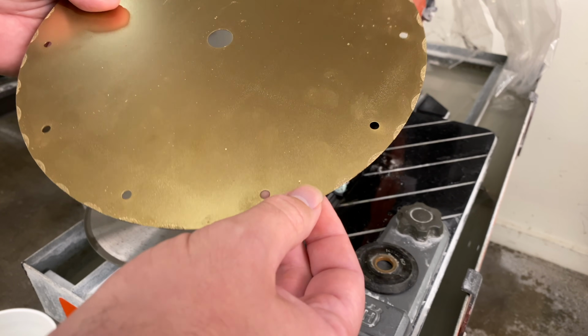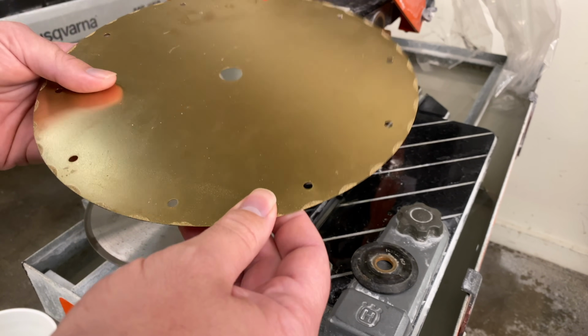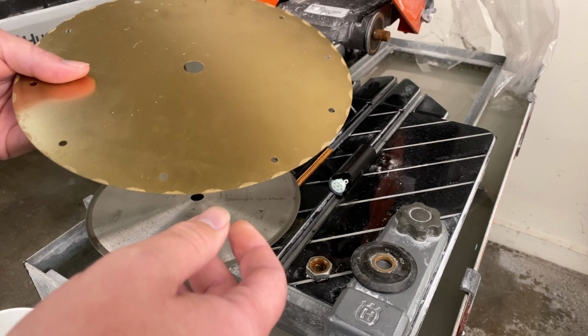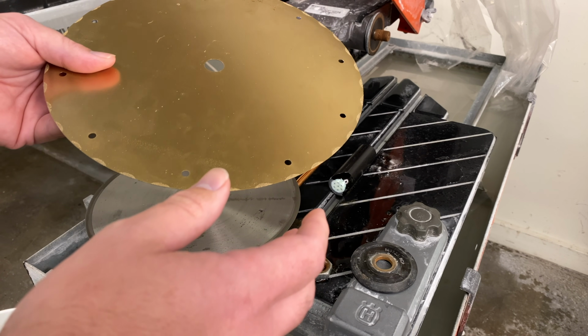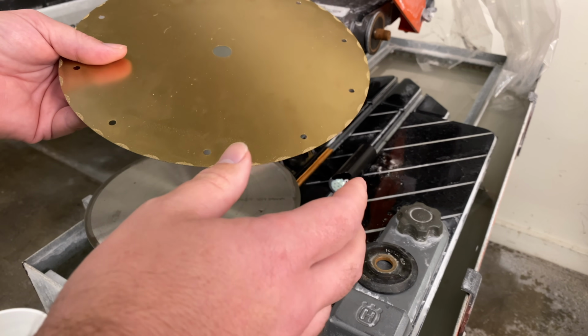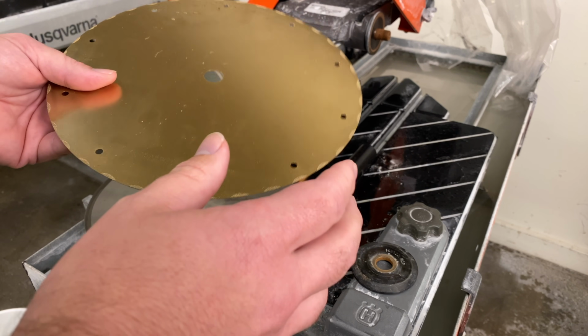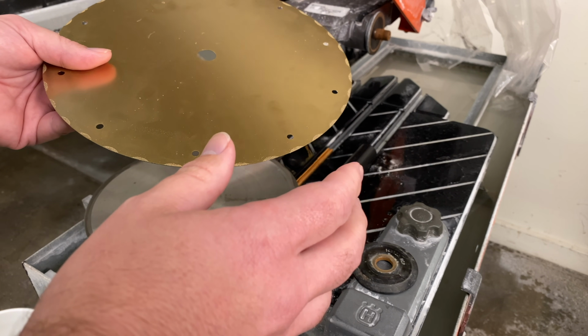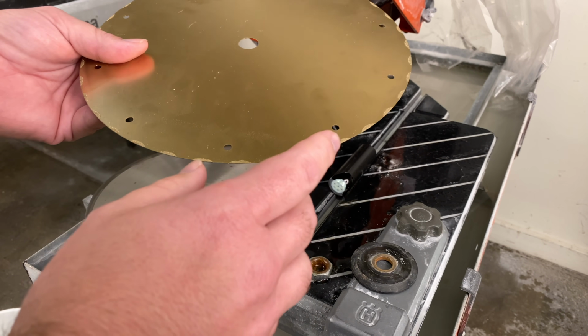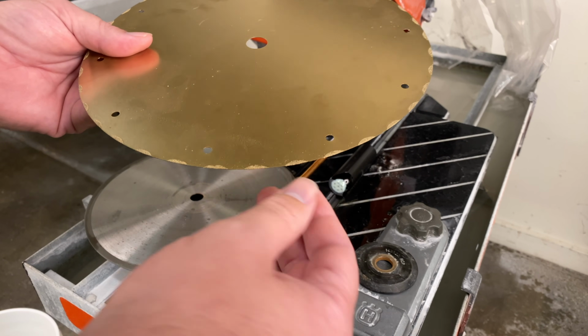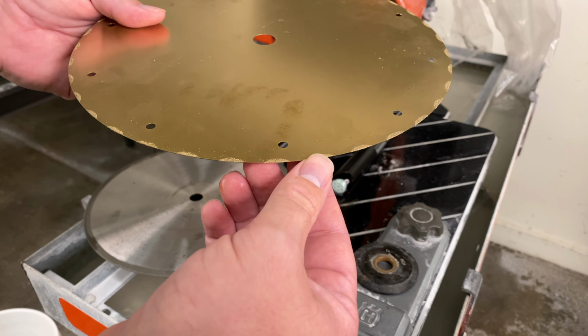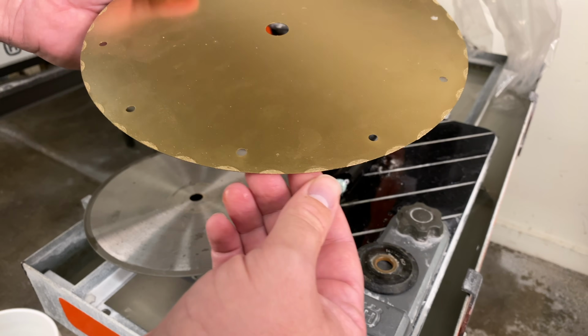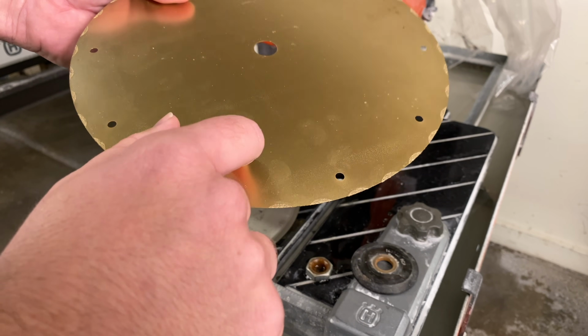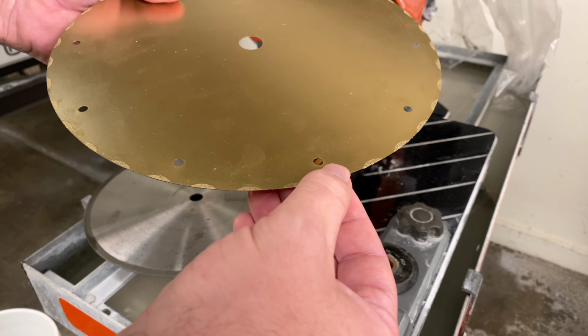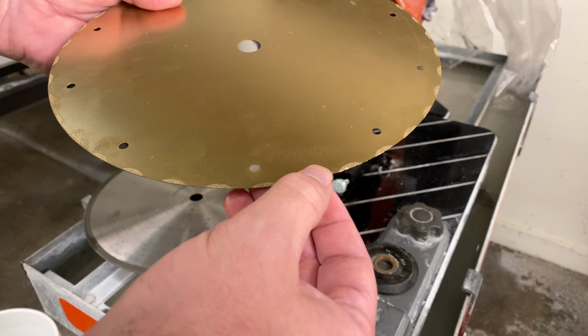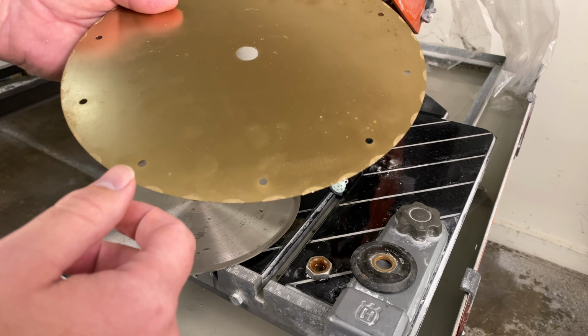So the difference between the electroplated and the sintered diamond is in that softer kind of bronze metal. As you cut with it, the diamonds are going to shift slightly in that metal, so it's not quite as aggressive a grind or a cut as you would see from this blade, which is an electroplated blade. Now these little dots or spaces of diamonds here are plated diamonds onto the substrate with nickel. So these diamonds do not move. There is only a single layer of them. So once they wear out, this blade is done.